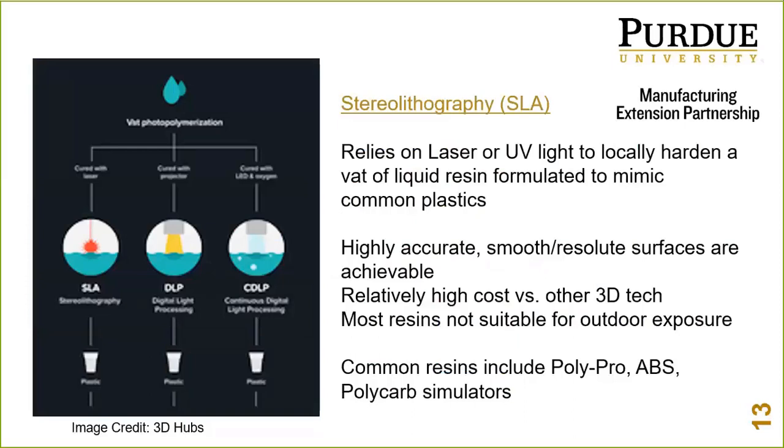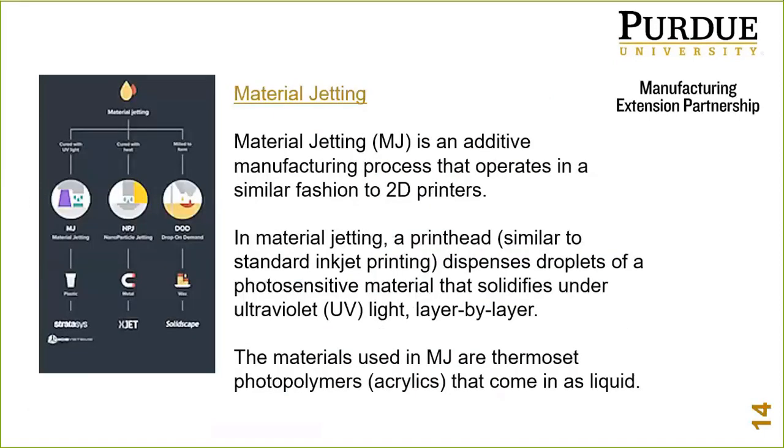This is an exciting area especially for material development — speeds have gotten better certainly. Material jetting, with tiny droplets dispensed from an ink head, offers really high resolution and accuracy. It's great for models and mid-stage prototypes where you want to see details without being distracted by layer lines. It's a light-based technology with UV light curing resin in real time layer by layer — mostly acrylic-based. You can achieve great transparent and translucent parts, making it a good application where glass or acrylic is traditionally used.